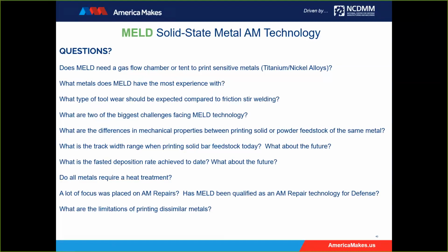And the answer is kind of yes across the board, but let me see if I can peel that onion back a little bit. I'm going to use aluminum as the example, basically because we've hit the 1000 through the 7000 series, some unique blends, and I mentioned NAB, nickel aluminum bronze. We can work with you to do an initial test specimen. You come back and say we'd like areas for improvement in these areas in order to hit our sweet spot. We can do parameter optimization. It's really not that difficult. It's a torque and linear force combination. So we could do a series of tracks at different torque and linear force combinations. Again, now we're starting to close in on the best fit parameters for the specific material that you want.